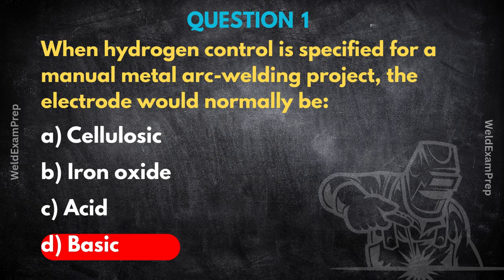When a specification calls for hydrogen control, it's because the cost of failure is just astronomical. This whole decision is driven by one threat: delayed hydrogen cracking, DHC. We hear about DHC all the time, but why is it so insidious for an inspector? Because it doesn't happen when you're watching. That's the key. Hydrogen, which mostly comes from moisture in the electrode coating, gets absorbed into the molten weld. Okay. But then as the weld cools down, those hydrogen atoms get trapped. They get stuck in the microstructure, especially where there's high stress. So the cracking can show up hours or even days later.